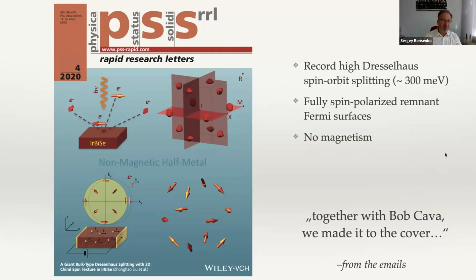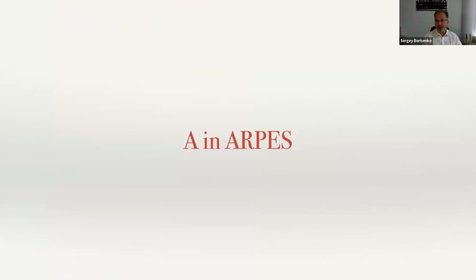I just wanted to hear your opinion, especially about the possible superconducting state, because this could be dependent on doping. The pairing could occur within the Fermi surfaces, or if the doping is very small, as I said, the electrons from opposite Fermi surfaces will pair. So I think the superconducting state would be very interesting. Good, so that was the iridium bismuth-selenide, which we called non-magnetic half metal. And now I switch to more technical things.